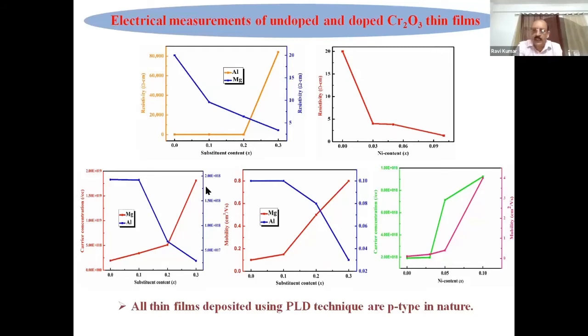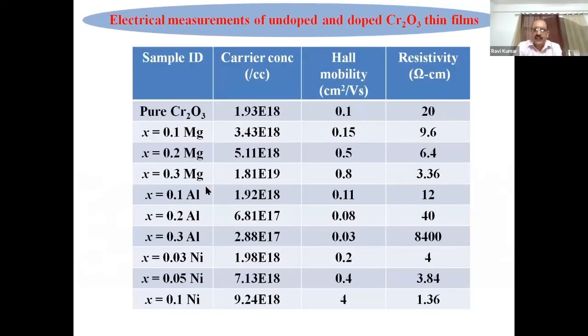I have tabulated the results in this fashion. If you look at the pure system, it has a resistivity of around 20 ohm centimeter. While substituting magnesium, you can go down to 3.36 ohm centimeter, which is very good. The conductivity is good, like a metallic conductor, though they are showing semiconducting behavior. Then the mobility is 0.8, very small.